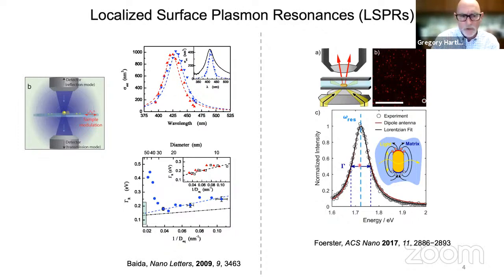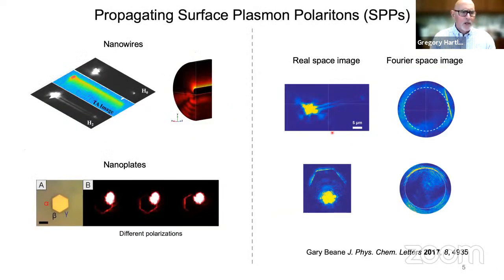Okay, so I'm actually not going to talk about localized plasmon resonances, although we've done a little bit of this work. I'm going to talk about the other type of plasmons, which are propagating plasmons. If you have an extended metal nanostructure like a film or a nanowire or a nanoplate, you can also have plasmons that move along the surface of these structures, and these plasmons have a definite momentum. Because they have momentum, it's sometimes a little tricky to couple light to the motion of the electrons because you have to match momentum. One way that you can conveniently do that is to look at a nanowire or a nanoplate under a microscope and focus your laser beam at the end of the nanowire or the edge of the plate, where the broken symmetry relaxes the momentum matching considerations, and then you can excite these plasmon modes.